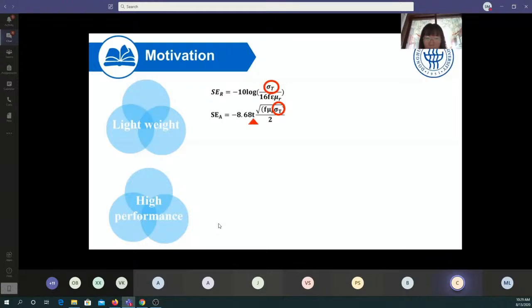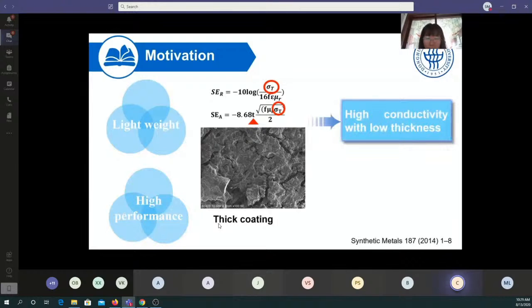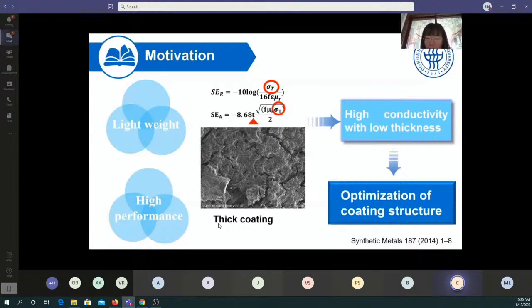Therefore, researchers will increase the thickness of the coating, which will decrease the performance and increase the weight. So if we want to achieve lightweight and high-performance shielding materials, we need to achieve high conductivity with a thin coating. The optimization of coating structure is one important method to achieve lightweight and high-performance EMI shielding coatings.